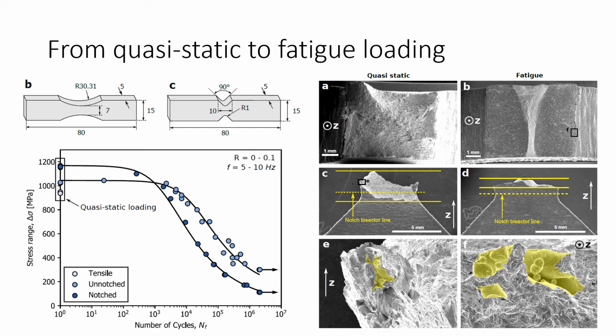However, it seems like the fracture surface is controlled by the fact that the defects are present in the downskin region, as the surface is ranging across or higher towards the downskin region. And in both cases we have defects in the fracture surface.